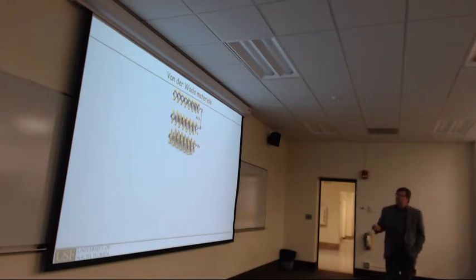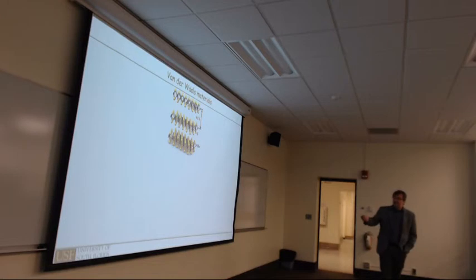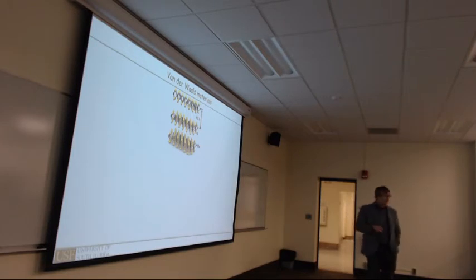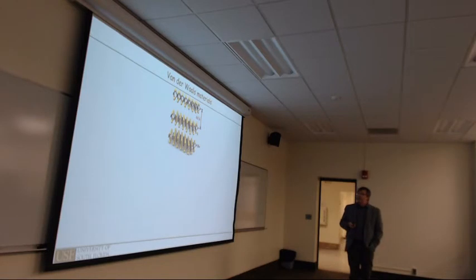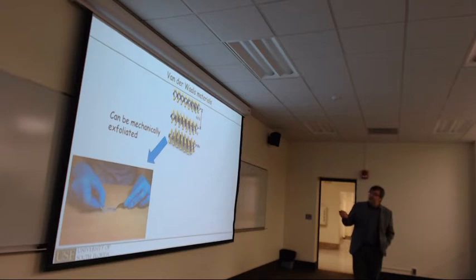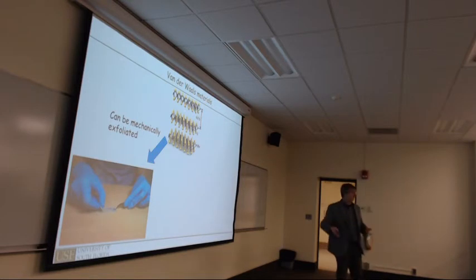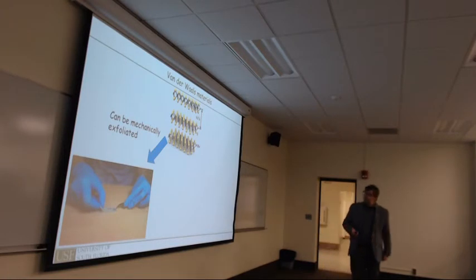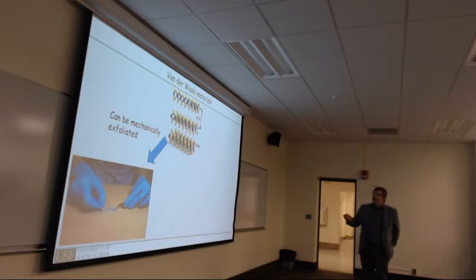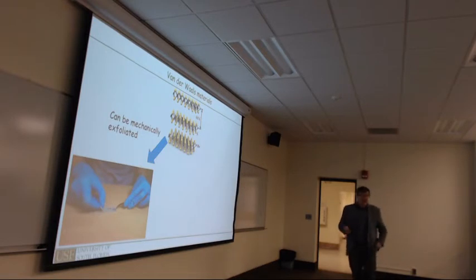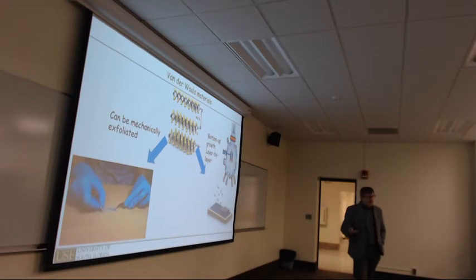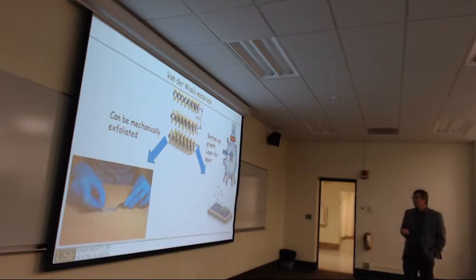Well, transition metal dichalcogenides, as I said, are these tri-layer structures with metal atoms sandwiched between chalcogen atoms. And then in the bulk material, like here for molybdenum disulfide, they form a three-dimensional structure where you have this van der Waals gap between the sheets, and that is the 3D material. You can use those crystals. Molybdenum sulfide is something you dig out of the ground. It's a mineral you can find, or you use it in your car engine as a lubricant. So you can take that bulk crystal and exfoliate it with the famous Scotch tape method. Just peel off layers, and if you peel it often enough, then you may end up with a single layer and then characterize those. In my research, I want to grow them directly,